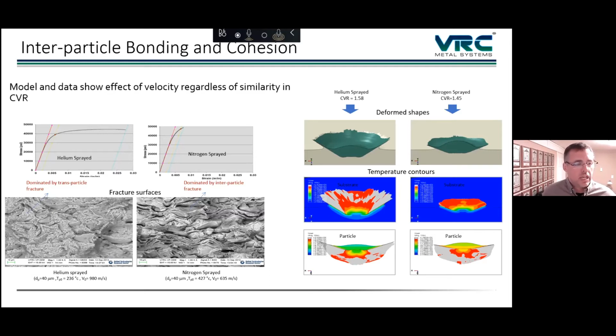And what you can see with these two is much more ductility in the one on the left, which is the helium sprayed, high velocity, low temperature. And if you look all the way over to the right, you can see examples of the FEA models for these two conditions. And you can start to see why we're getting that better interparticle bonding in the helium sprayed condition, for example.